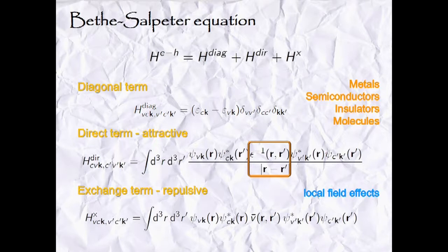It's more or less because if the metal is good, you can do so. If you have bad metals, there could be also excitonic states, maybe not at the absorption onset, but at higher energies or in core states. Semiconductors, we have smaller electron densities, so the screening is less efficient than in metals. And here we have exciton binding energies in the valence range of the order of a few milli-electron volts. If you go to the core, these are higher.